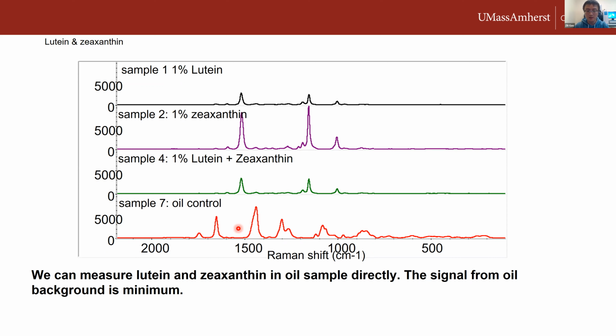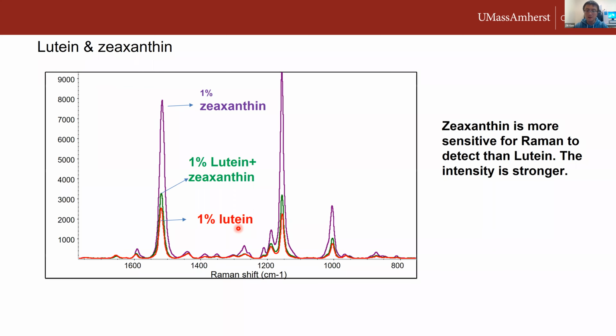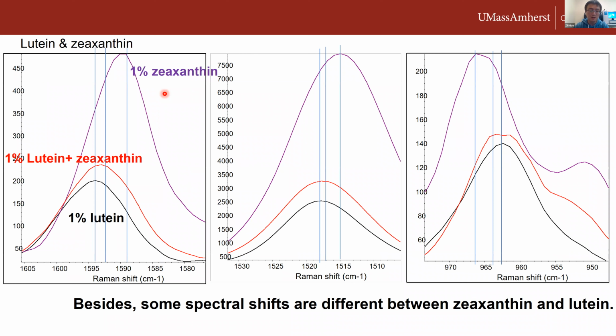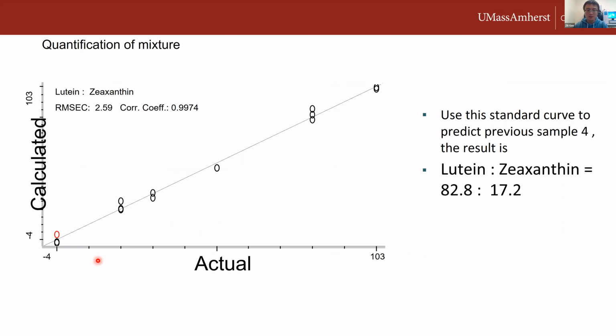When we enlarged this spectrum, we found that zeaxanthin has more sensitivity to Raman measurement, as demonstrated by 1% of this compound having significantly higher Raman intensity. Even though these two chemicals are highly similar, we still found that they have peaks at different wavelengths. For example, zeaxanthin had a peak at 1590, and lutein had 1595. So by identifying these peaks, we will be able to identify them in the mixture form. And after calculation, we found that theoretically we have 83% lutein and 17% zeaxanthin, and this corresponds to the actual amount.